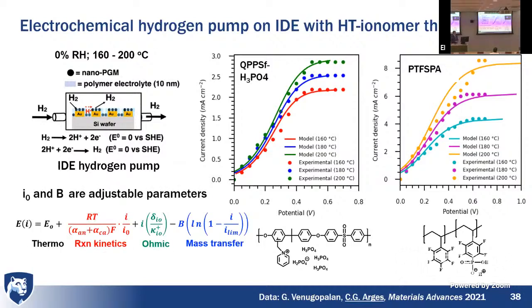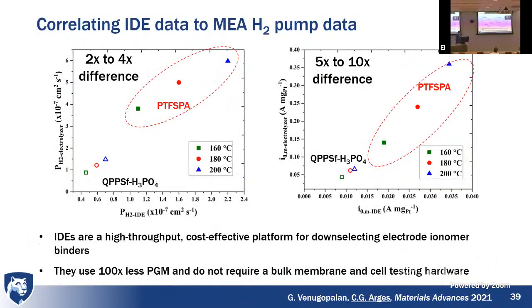And we've taken all that data we collect in the lab, and we can fit that to our current distribution model or voltage loss breakdown model, and deconvolute the contributions in these curves from reaction kinetics, ohmic losses, and mass transfer. And what I want to tell you here is that, okay, like in permeability, we can look at the limiting current in the MEA, the actual cell, versus what's on the IDE. And the data that we get on those little circuits, right? There's only a 2 to 4 factor difference between what we measure on the little interdigitated electrode versus the MEA with different materials as a function of temperature.